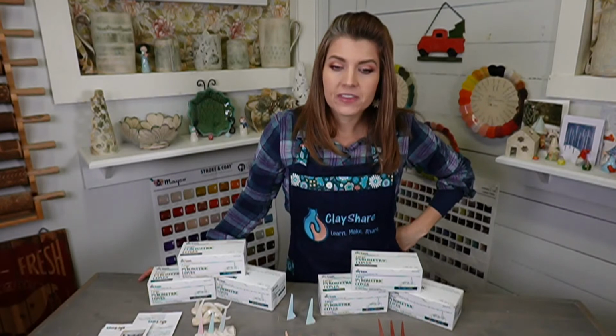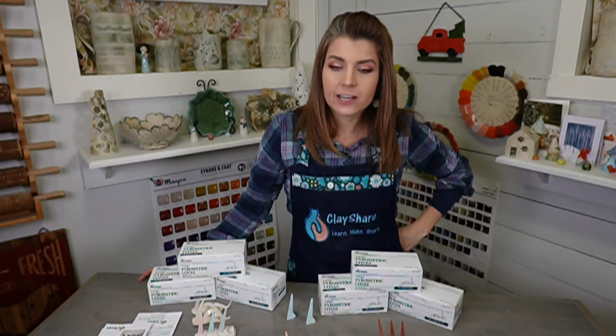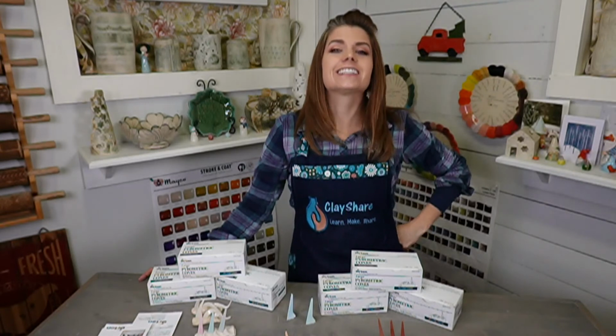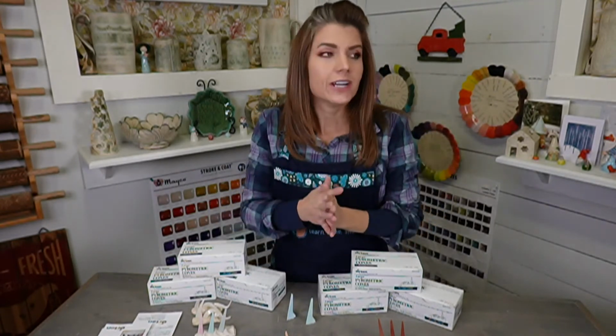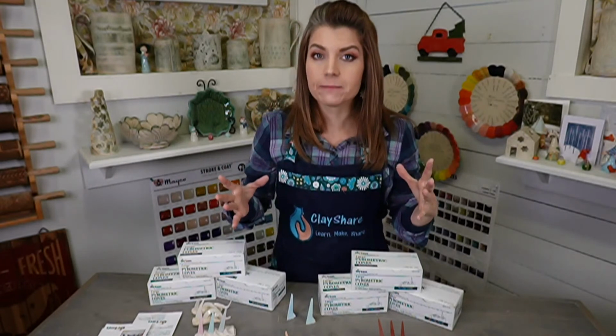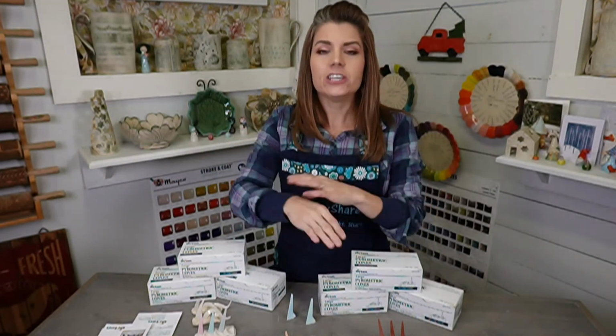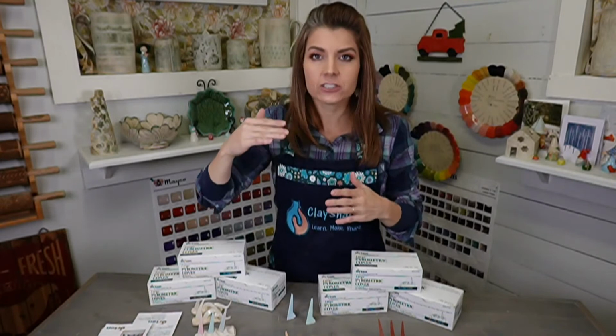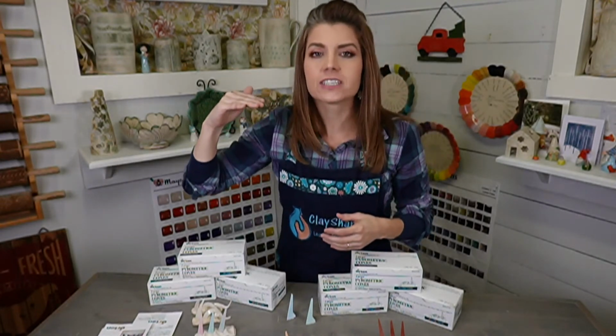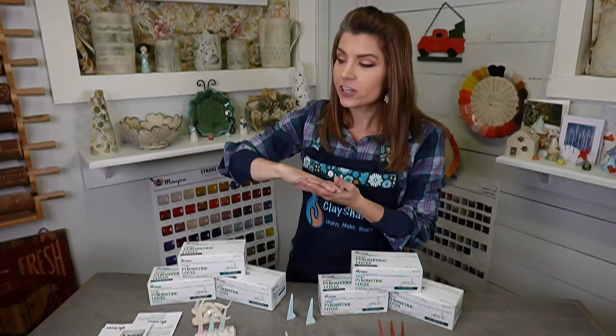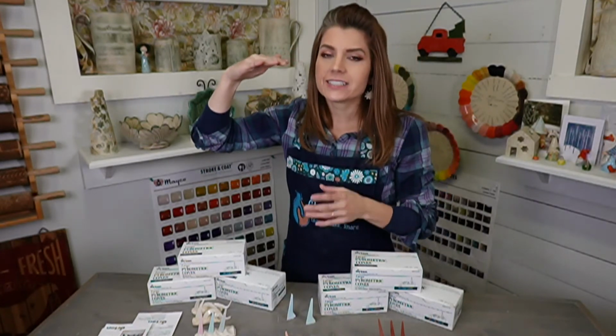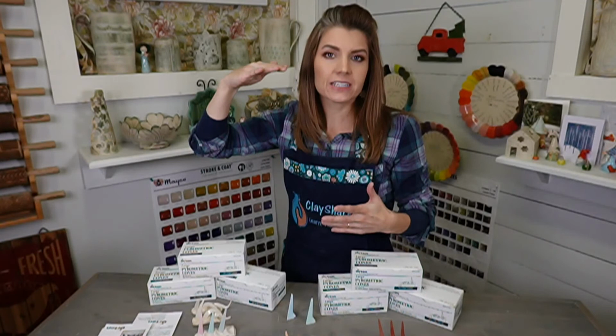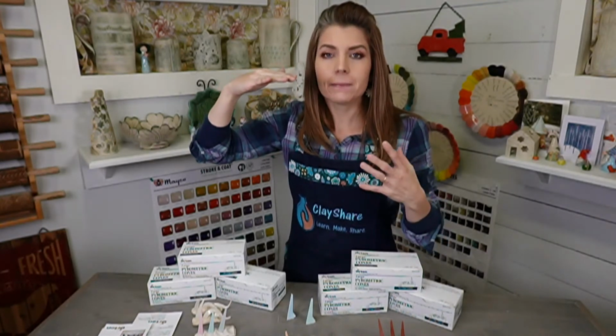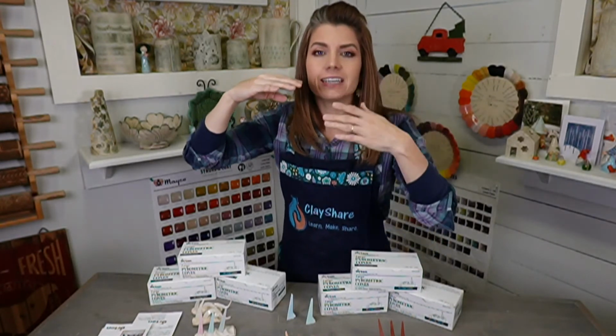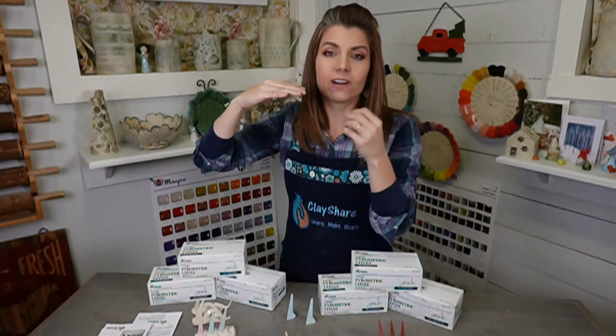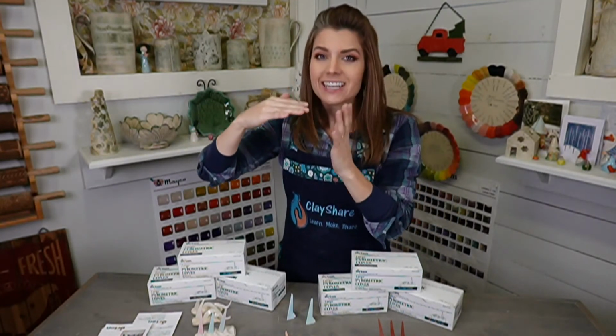So firing to a lower temp than the cone temp can still melt the cone if the temp is held long enough. Chris, exactly. So when you do, say, a cone 5 firing, right? So you do a cone 5 firing, and you hold that for 30 minutes at the end. So you get to that top temp. Cone 5 is 2167 Fahrenheit. So you fire your kiln, it gets to 2167. Instead of it shutting off, you hold it for 15 minutes, hold for 20, hold for 30. What's happening is it's staying at that temperature, but the heat and time is still working on your glazes. So your kiln is actually getting hotter.